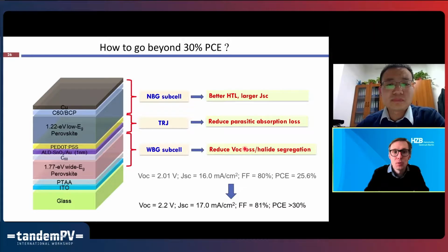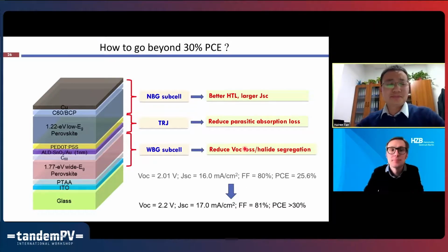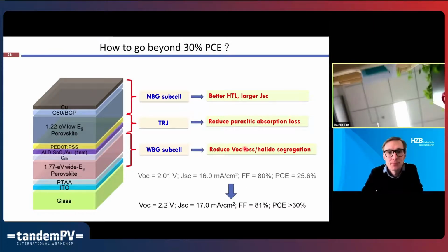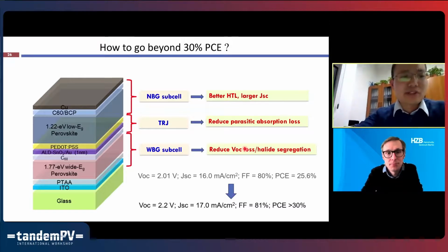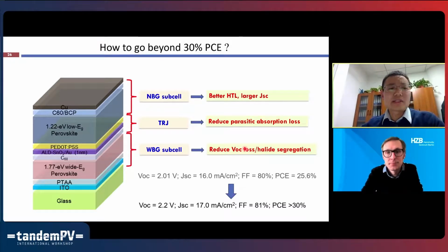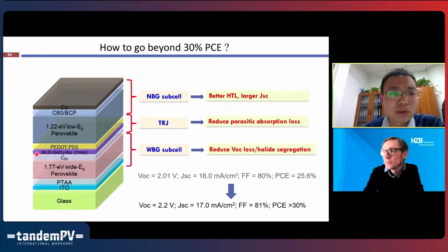So this is a very good question. Yes, I think the protection of the top cell is very important if you want to do the bottom subcell by solution processing. Typically we found that this atomic layer deposited tin oxide is very critical.